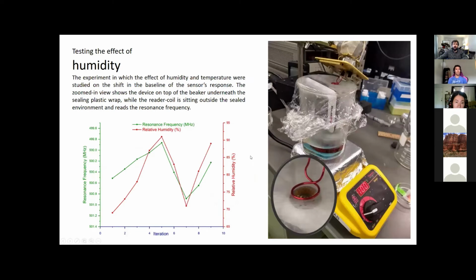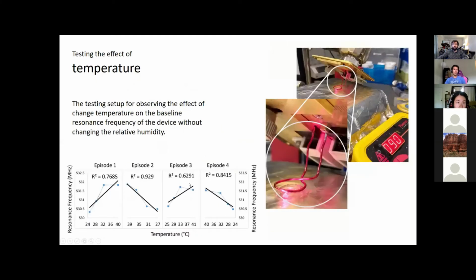And then I wanted to see what happens if the humidity in the environment changes when you have these devices on. So I changed the relative humidity from 70 to 90 something percent, 92 or 93, which is very typical in Michigan, I guess. And I observed that when you change the humidity, the resonance frequency follows that fashion. And when you decrease it, it drops back, and the same goes again. So I infer from this experiment that you can compensate. If you have a humidity sensor in, let's say, your goggles or your electronics, and you know what the relative humidity of the environment is, you can recalibrate your resonance frequency every now and then. So I wouldn't be worried too much about change in humidity.